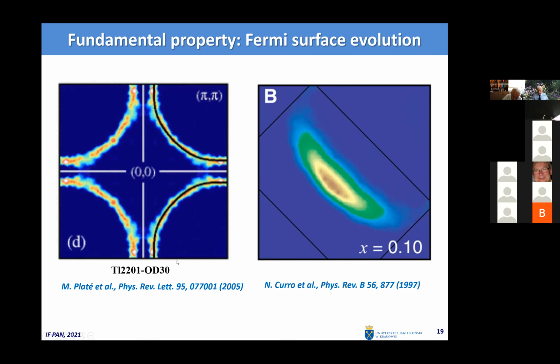Whereas if you go to lower concentration, here instead of delta it is x, it's 0.1, 10%. It gets broken, this beautiful hyperbola-like shape, only here in the nodal direction, which means the diagonal, where the superconducting gap is 0. Even in the normal state, here is always a metal in the superconducting normal state. So only this state survives here, whereas the rest disappeared.